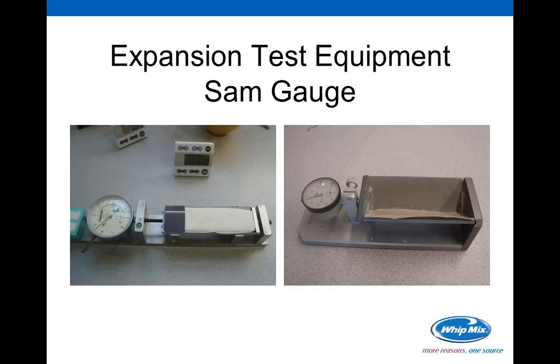Remember, this is a percentage. This number is a percentage of volume. So if you're using 200 grams of material, you're going to get a larger expansion linearly. It will still be point whatever percent, but the actual movement will become larger. And the larger the volume of material you use, the larger the actual movement will be as a percentage. So you need to remember that as you look at the percentages that are being reported, and then as you think about how large you're making your individual model.